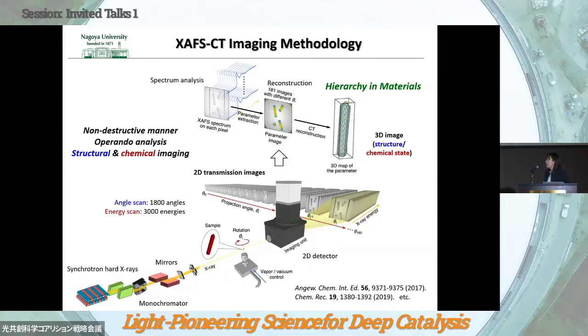And finally, we can analyze this huge data set of two-dimensional transmission images, and analyze the spectra in 2D, and we construct these parameters. Finally, we can get a three-dimensional image of the structure and the chemical state of materials, which shows us the hierarchy in the materials. This is non-destructive, and we can apply it to operando analysis using hard X-rays. It is a quite powerful tool for structural and chemical imaging of catalysts and materials under reaction conditions.